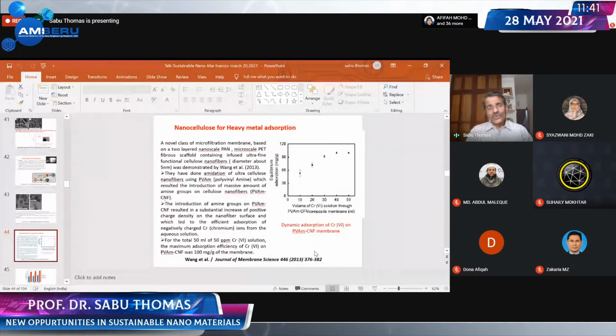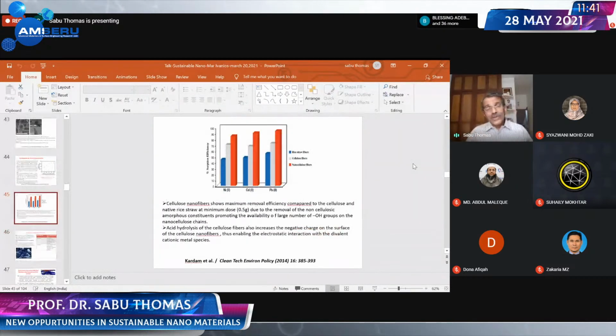Let me show you another interesting work where you can remove chromium from water. Chromium 6 is electronegative. What you have to do is modify the nanocellulose with amine group, polyvinylamine. And when you put amine groups on the surface of nanocellulose, it becomes electropositive. And there can be electrostatic interaction between chromium and nanocellulose, and you can remove it. You can see the equilibrium absorption process. Similarly, you can remove nickel, cadmium, and lead.